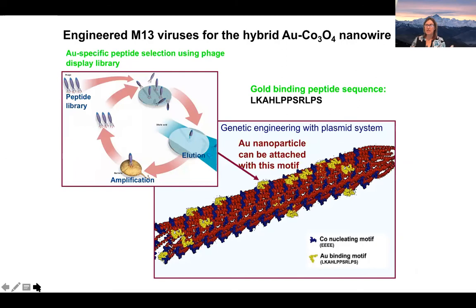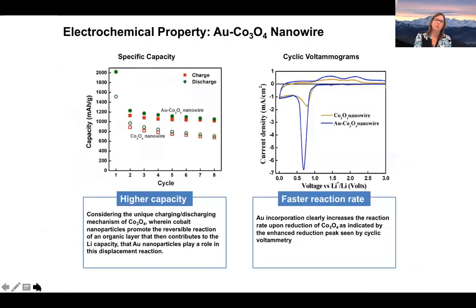But then my students were very clever, and they go, okay, well, we only used 1 gene. What if we go in and give it a second gene? We know that we'd like to have a good ionic conductor, which in this case is going to be our cobalt oxide, and we want to have a good electrical conductor at the same time. What if we went back and gave it one of those sequences we know are good at growing gold, so we could grow both materials simultaneously? And that's what they're able to do.